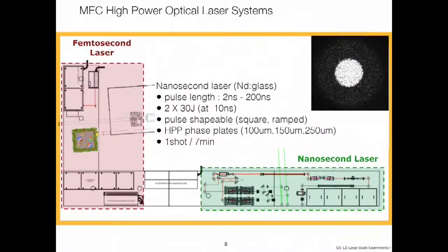The second system is our nanosecond laser system. So this is a high energy system. We have 2 arms that go into the chamber, which both have 30 joules of energy. The pulse length is about 10 nanoseconds. It can be tailored, so we can make it shorter or longer, from 2 to 200 nanoseconds. We can put specific shapes in that temporal profile to ramp it to get other shock profiles.